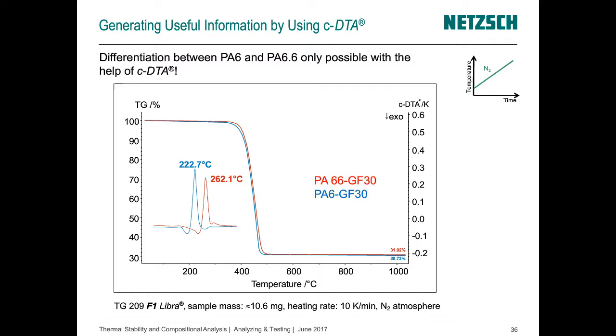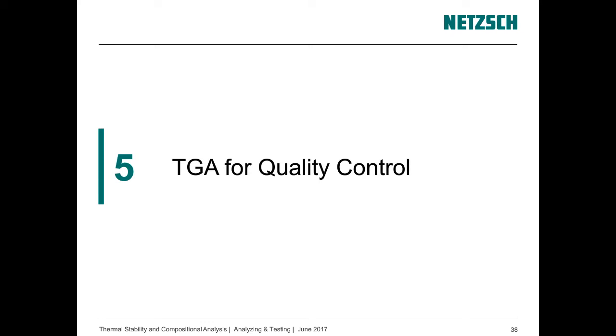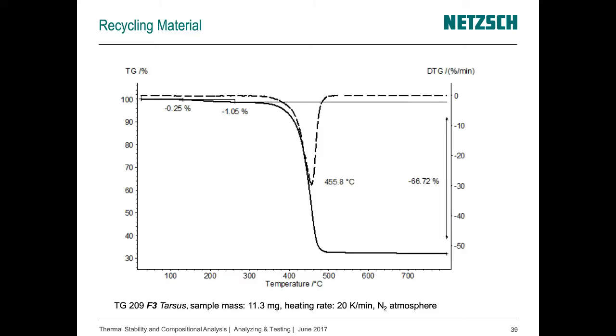I promised you to show you also an example how TGA can be used for quality control purpose, and this is what I will show you now. Let's say we have any kind of recycling material represented by the black curves here. This is the TG profile with a main mass loss between 350 and 500 degrees C. The corresponding DTG peak is at about 456 degrees C.